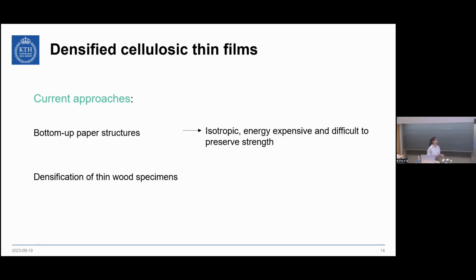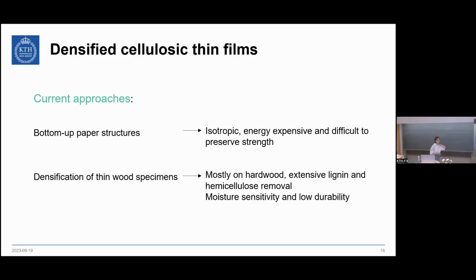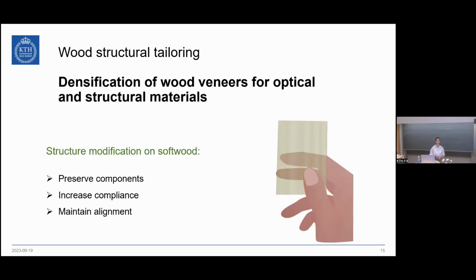Alternatively, we can directly densify thin wood specimens, and this has been done in literature mostly on hardwood, in the majority of cases on balsa wood. And this again requires extensive removal of components, mostly lignin and hemicellulose, so that the material can be more compliant to densification. However, this normally leaves just a cellulose scaffold, which means that it is usually moisture sensitive as well as shows low durability. So in our case, we focused again on a top-down approach on thin wood films.